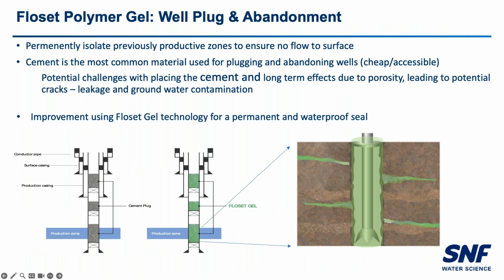So the first part of that talk was dealing more so with our flexible gels, again, something that starts liquid, forms a solid. We also have a new product that's relatively new. It's had some application in Australia and Europe, but not a lot of application yet in Canada. So this would be sort of a cement replacement. Again, we're looking to permanently isolate and control the zone, but still create some infiltration into the fractures and create a seal between the rock and the casing. So again, cement replacement. There's maybe some impacts on porosity and gas leakage through the system that we can improve upon versus cement. And again, we're looking for a permanent waterproof seal that allows us to abandon this well without using cement.